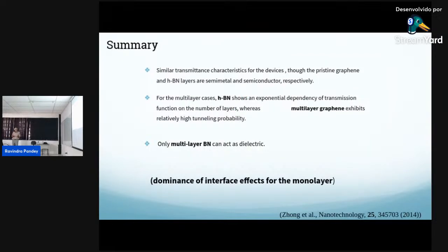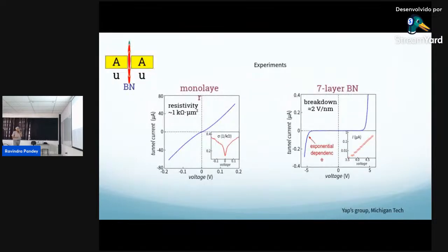So the message that comes out to you is, for nanomaterials, you can do whatever you would like to do, predict, do the calculation. But when you make a device out of it, we have to be careful about the interface effects. And we have to have a thick material if you really want to make these devices. And there's an experimental paper coming from our Michigan Tech group labs. This is a boron nitride. And you can see here in the monolayer case, a metal-like conduction. But when it goes to 7-layer boron nitride, it has diode-like behavior. What do you guys see?